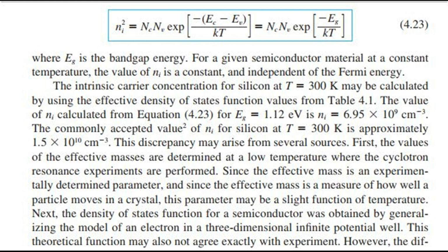For a given semiconductor material at a constant temperature, the value of ni is a constant, and independent of the Fermi energy. The intrinsic carrier concentration for silicon at temperature T equals 300 kelvins may be calculated by using the effective density of states function values from table 4.1. The value of ni calculated from equation 4.23 for Eg equals 1.12 electron volts is ni equals 6.95 × 10^9 per cubic centimeter. The commonly accepted value of ni for silicon at temperature T equals 300 kelvins is approximately 1.5 × 10^10 per cubic centimeter.